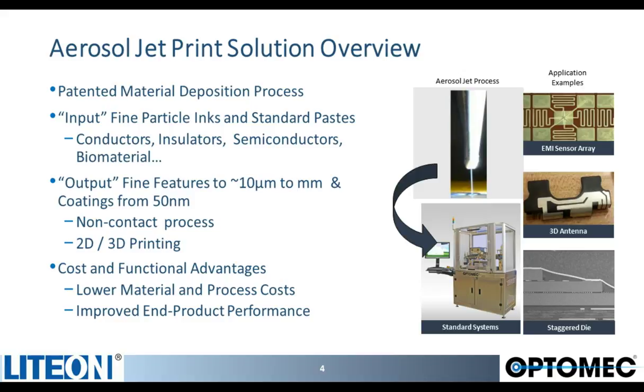So what that enables us to do is have a high standoff distance between the surface of the substrate and the nozzle outlet. So that distance can be anywhere between 1 and 5 millimeters, and while we maintain fidelity of that printed feature.